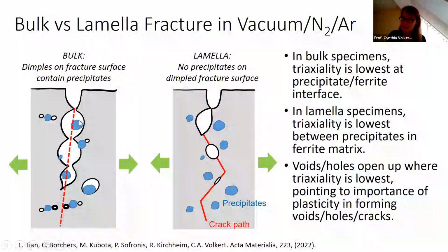And in the bulk stress state, that high plasticity region is at a precipitate matrix interface, whereas in the thin lamellas, that's in the middle of the ferrite grains. Because of the difference between the plane strain and the plane stress state, or because of the difference in the triaxiality, if we argue voids or holes will open up where the plasticity is highest, then we can explain both the bulk and the lamella case as being the same process governed by the same mechanisms. It's just that where the voids or holes are forming is determined by the stress state, which, as we said, is quite different in the two cases.